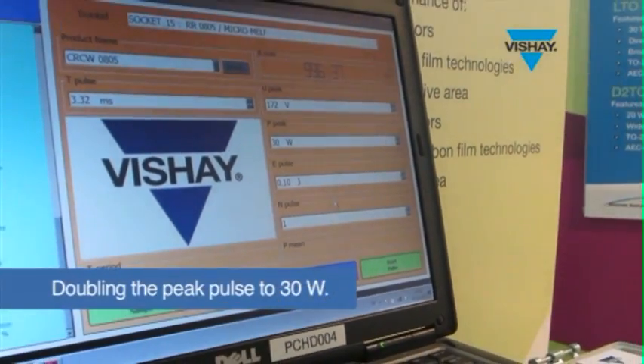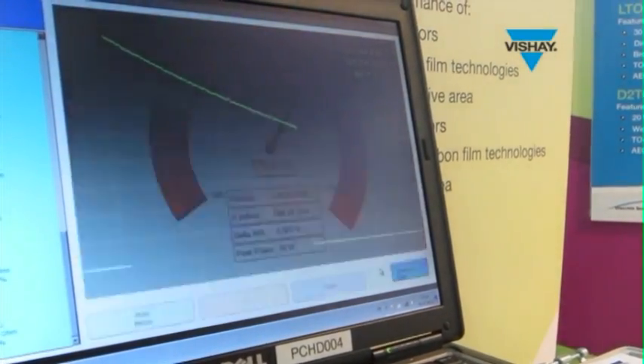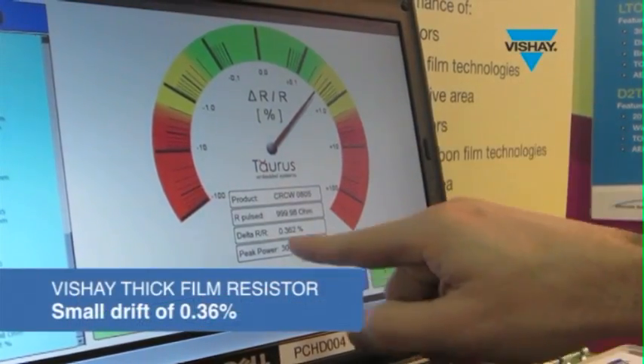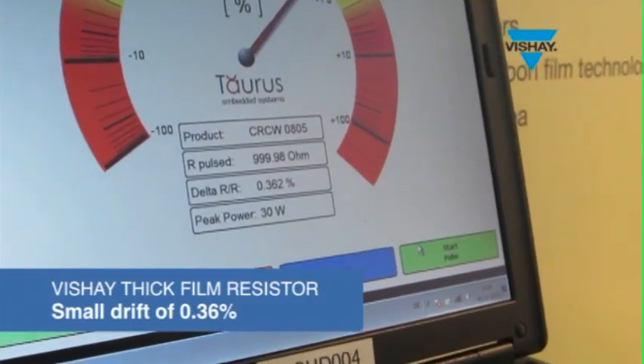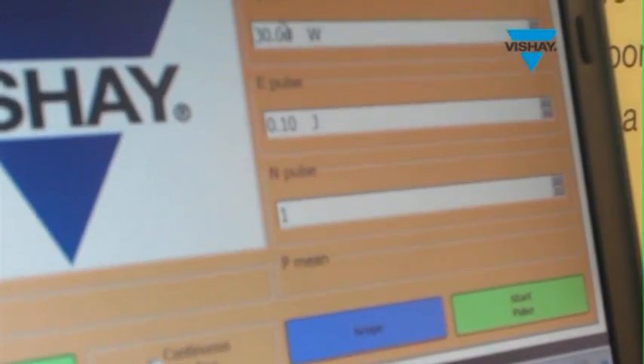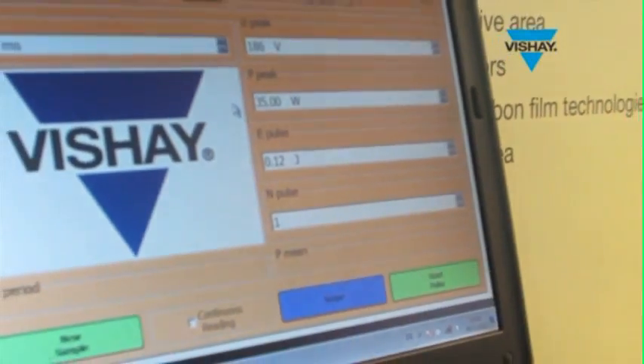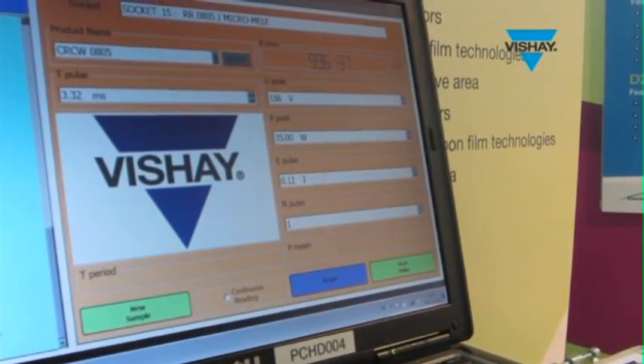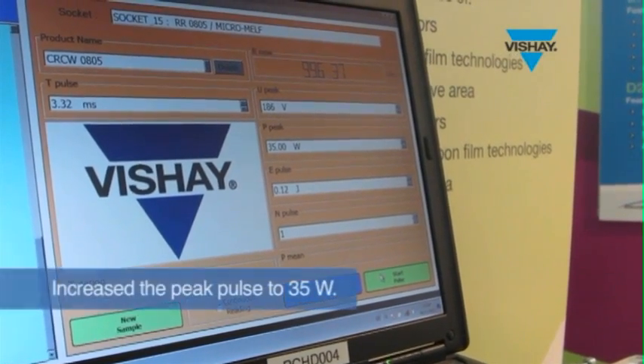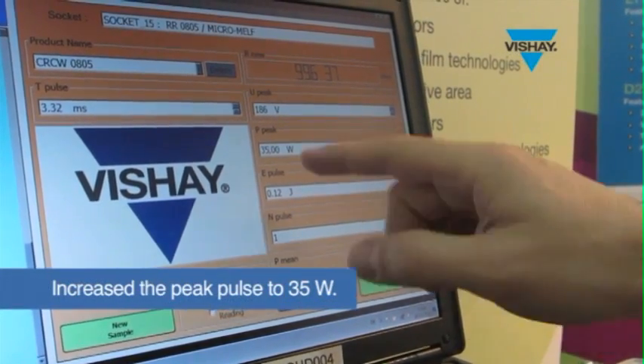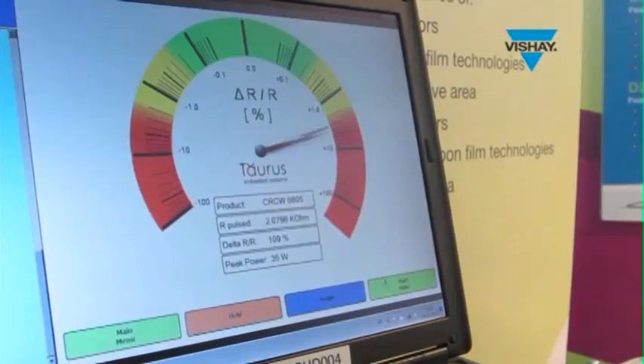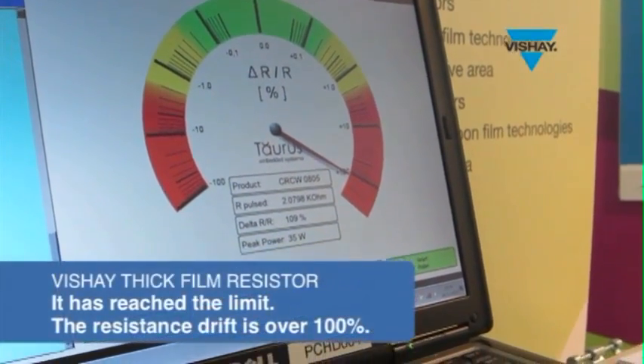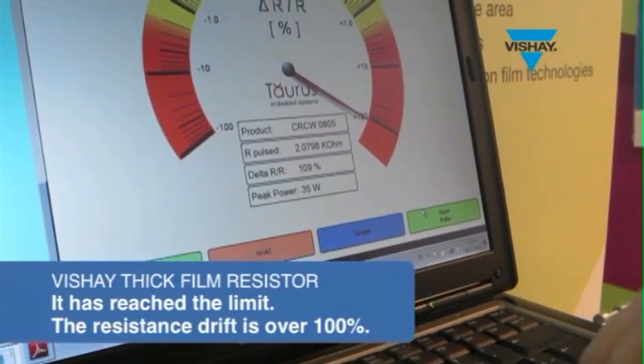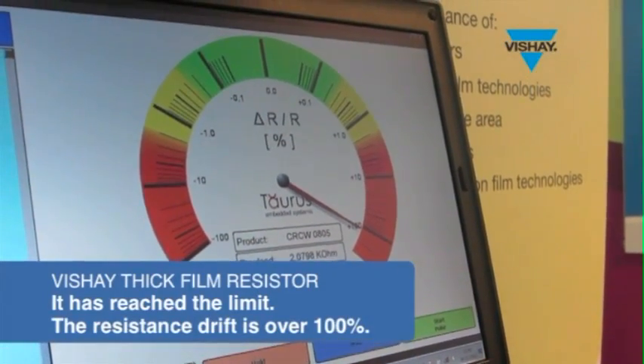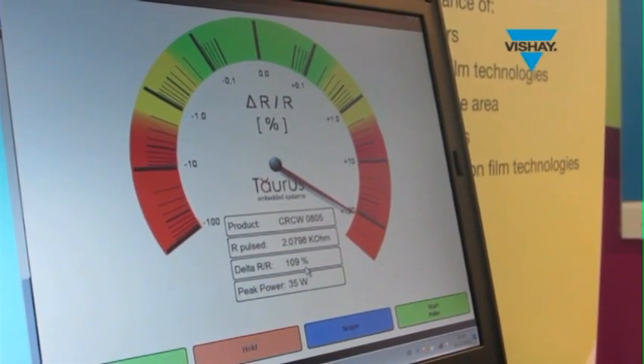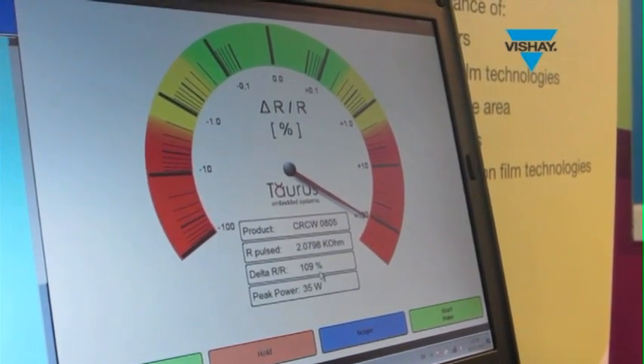And now let's double the peak pulse applied to the component, and for the CRCW, it's not too bad, it's around 0.36%. And actually, applying double the power compared to the non-name thick film, we see that the CRCW is surviving pretty well. And now let's increase it to 35 watts, and then it's about the limit of this component, with the resistance drift over 100%. So the component is basically open and no longer in working condition.